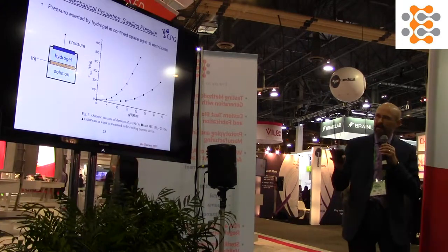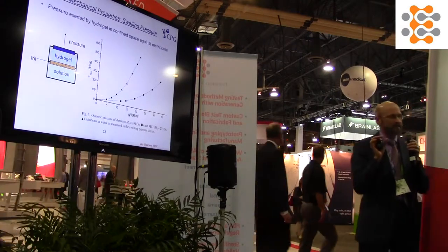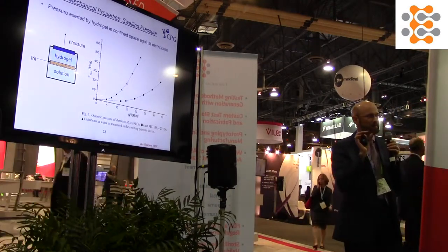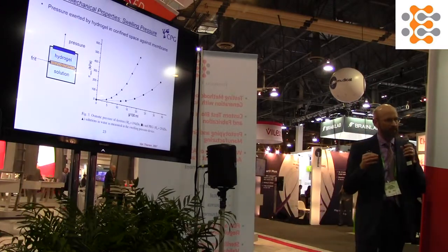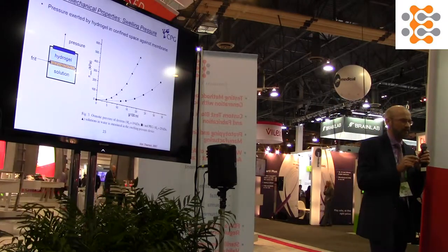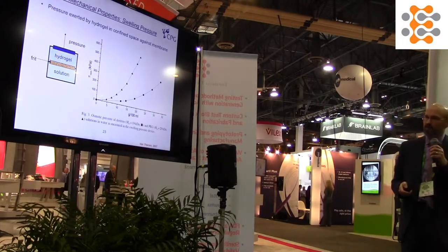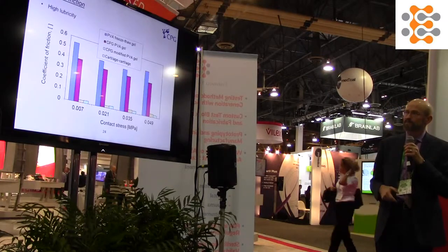Swelling pressure is something that one of our clients, who was making a mosaicplasty replacement, so just a focal defect plug replacement, hadn't adequately taken into account: how much swelling can occur with these hydrogels. They were constantly popping out of the knee joint when they started to imbibe the synovial fluid in the knee joint. So they now know to look at this.